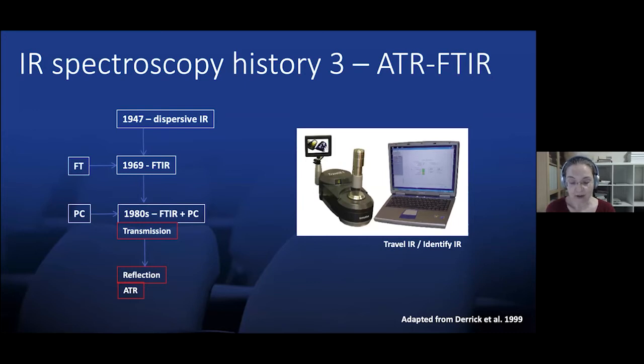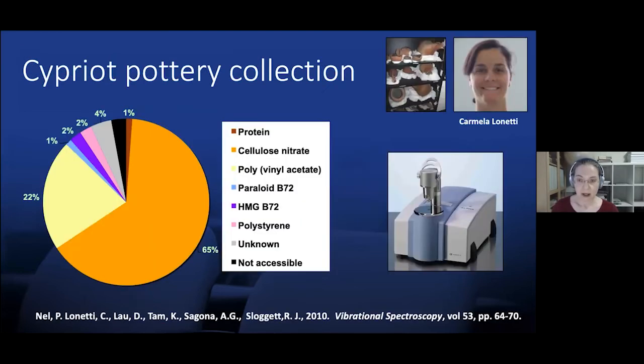The only problem I had with it was the diamond crystal was concave, leading to, if you were to measure a sheet, a significant indentation impressed onto it when analysed. So I was keeping my eyes open for a reflection sampling module with a flat ATR crystal. I found this with the Bruker Alpha FTIR instrument, which had a flat ATR module. I, in the first instance, rented the instrument from the company for about 1 to 2 weeks and used it to conduct a survey of the Cypriot pottery collection in the summer of 2009-2010.